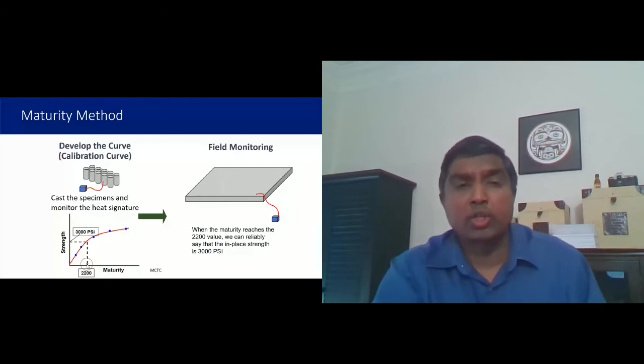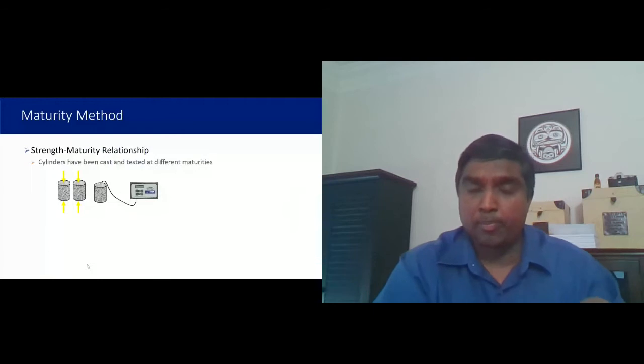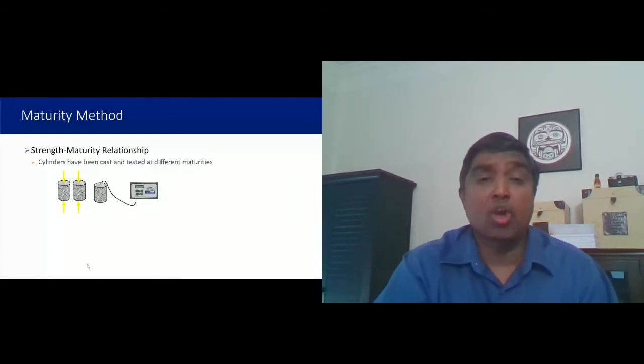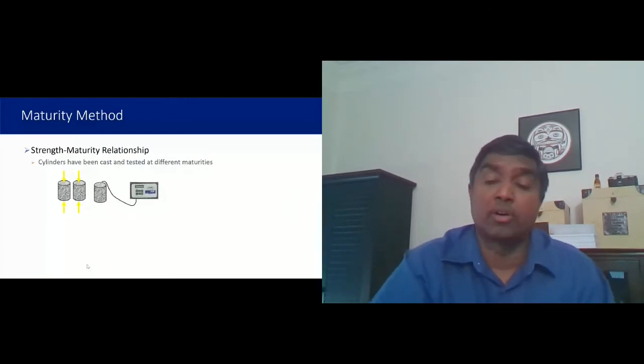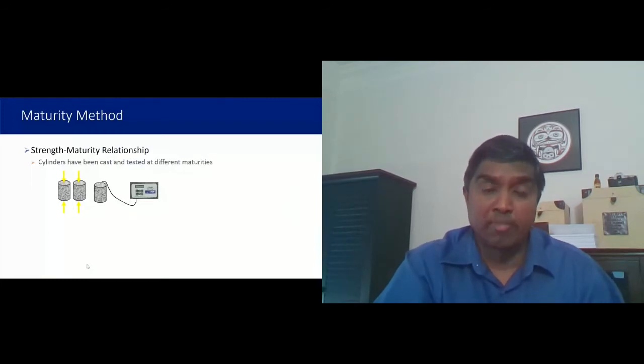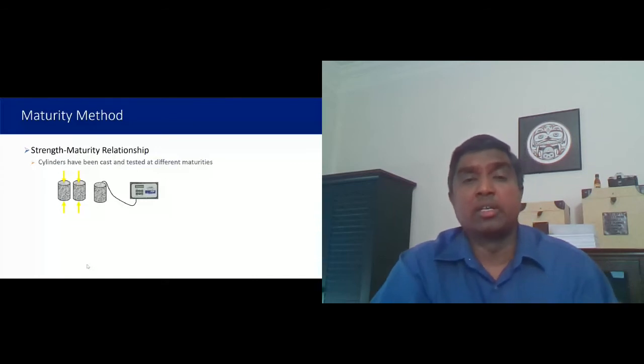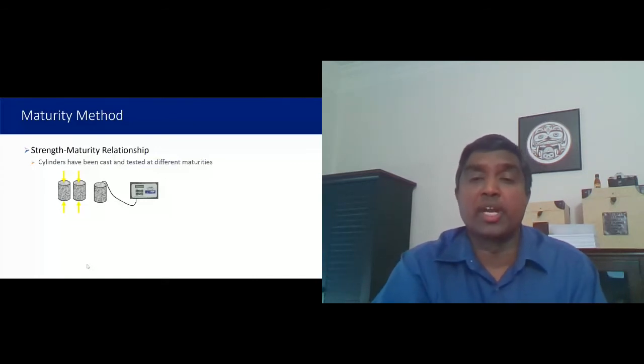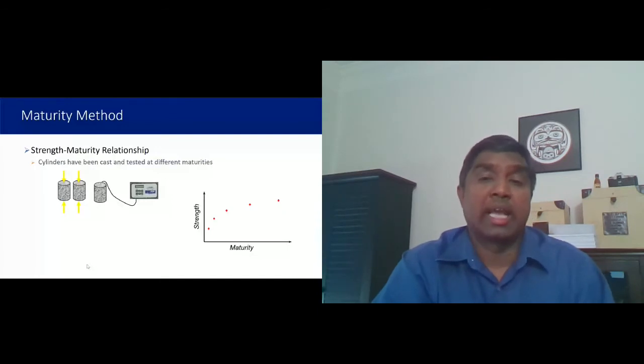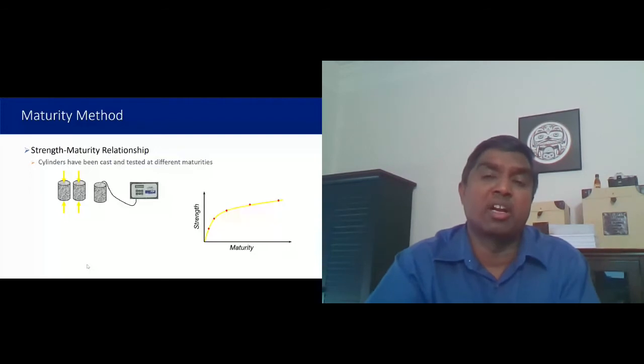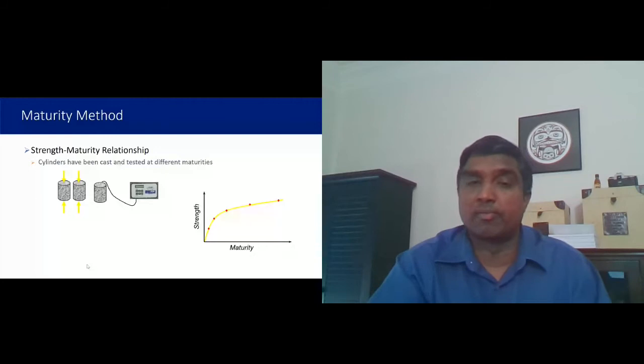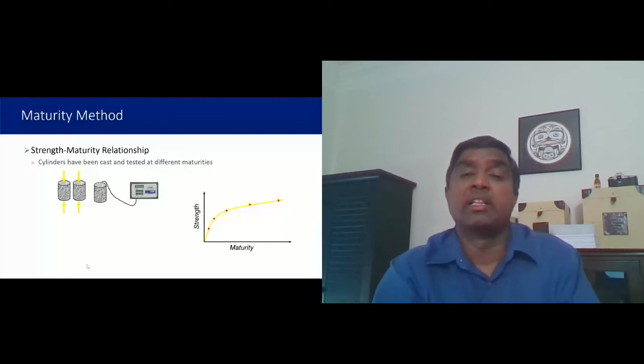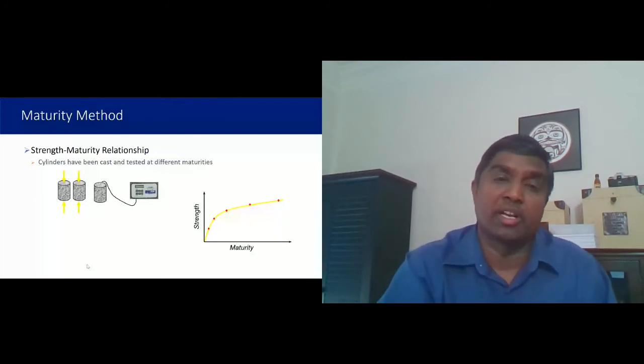So let me walk you through the process again. We cast a bunch of cylinders or beams, whatever strength you're looking for, and then put a temperature sensor or a maturity sensor in one of the cylinders or specimens. And as we obtain strength and maturity information, we plot a calibration curve. That's really all there is to it. The upfront effort is there a little bit, but once we have that information, we can use it for a number of days to estimate the in-place strength of pavement or any structure.